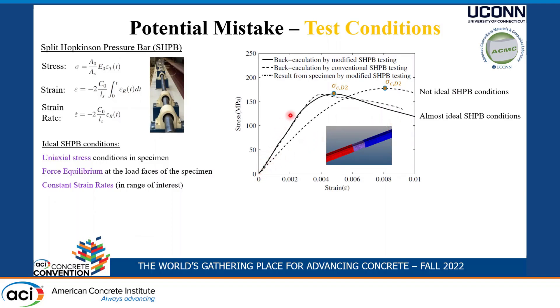Here is the real curve you would calculate under nearly ideal Hopkinson bar conditions in compression — stress versus strain, like a uniaxial compression test but under high strain rates — and this is the curve you would calculate using those equations when you do not have ideal conditions. In reality when testing experimentally, you don't know which is which, because what you get out of your test is the material behavior you calculate, not the true behavior directly.